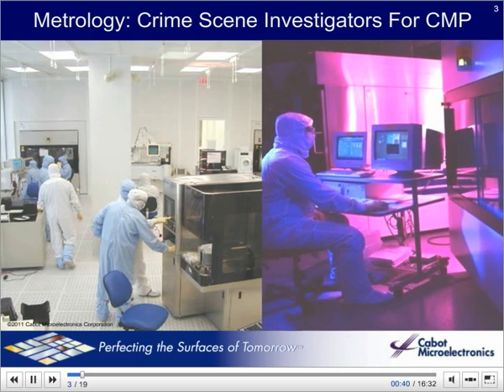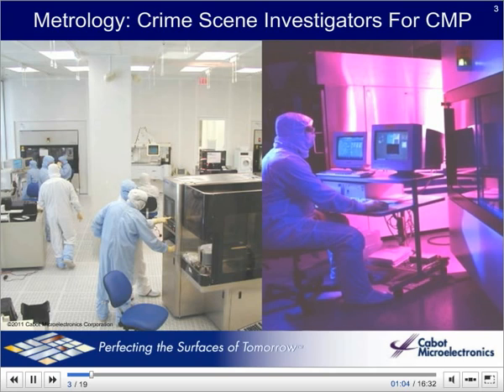Before we discuss all the things that can go wrong with CMP, it is important to touch on some very sophisticated and expensive metrology equipment and our dedicated and trained experts that use them. What we are often looking for are scratches, pits, debris, sometimes only a few tens or hundreds of atoms across. Our experts employ electron and atomic force microscopy and optical profilometry to measure flaws in the polished surface. Laser light is scanned at glancing angles along the surface, and the scattered light is measured to see whether there is a crack or residue. Multiple techniques are employed together to unravel the mysteries of CMP, and especially the causes and effects of pathologies.